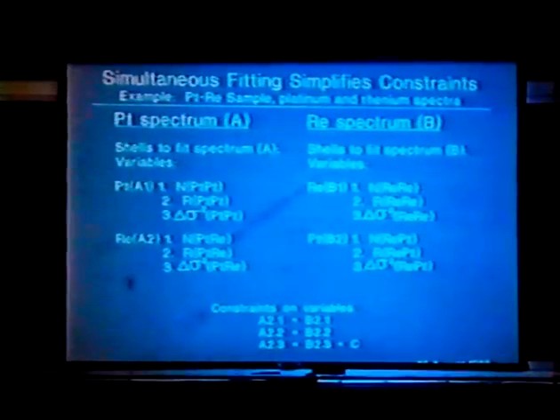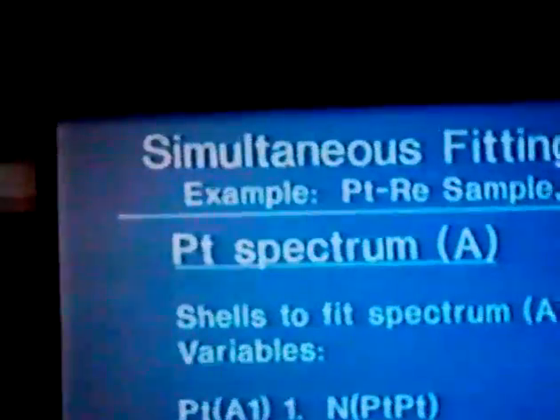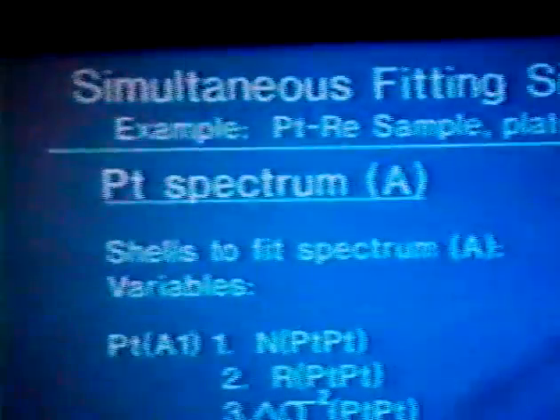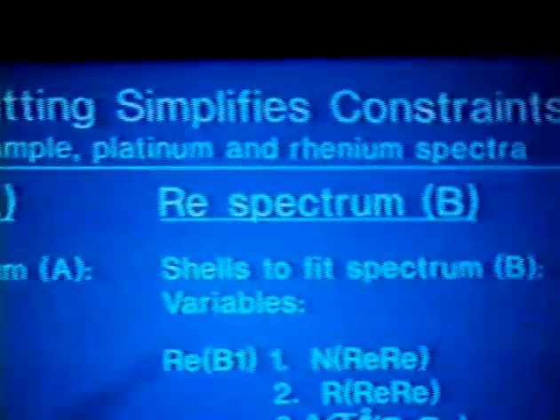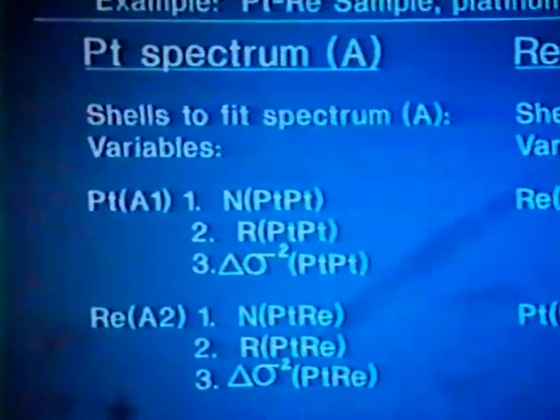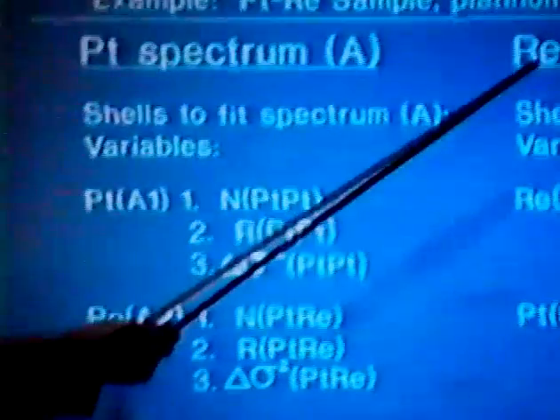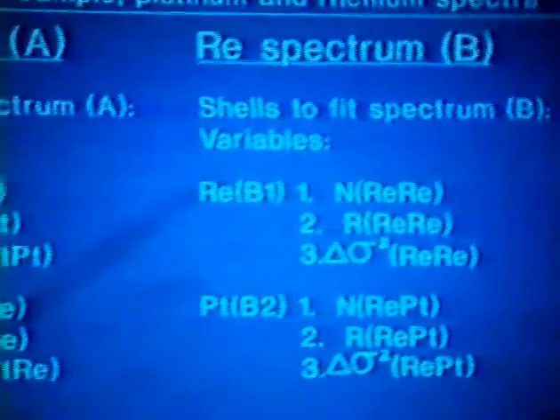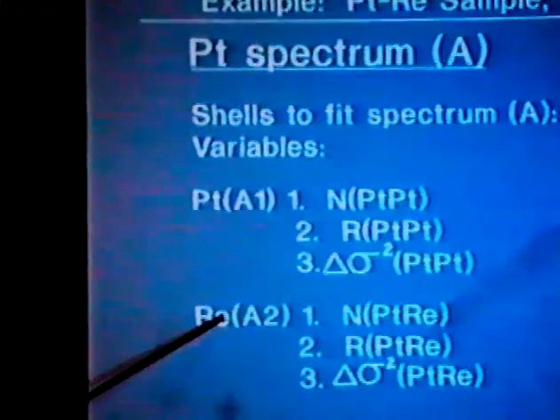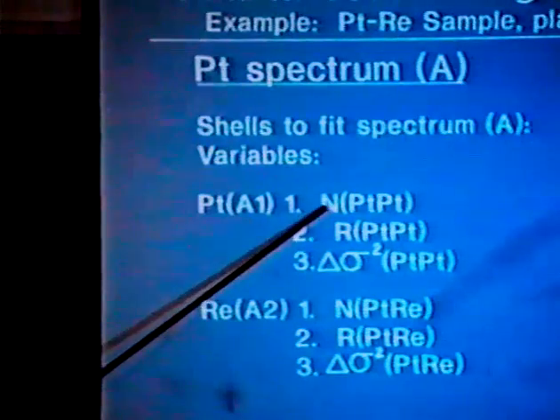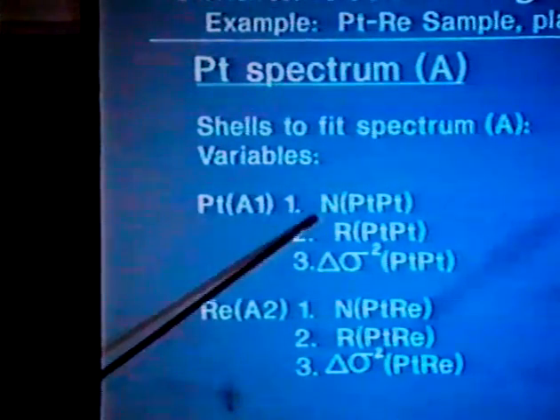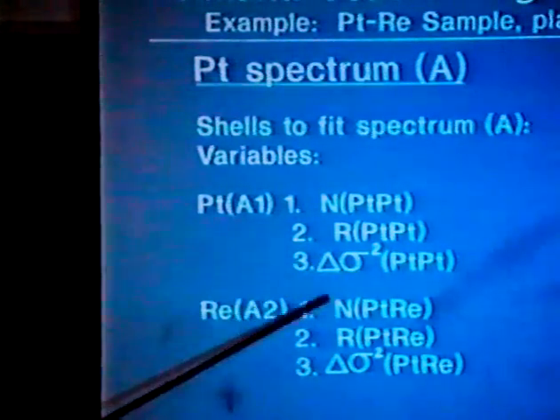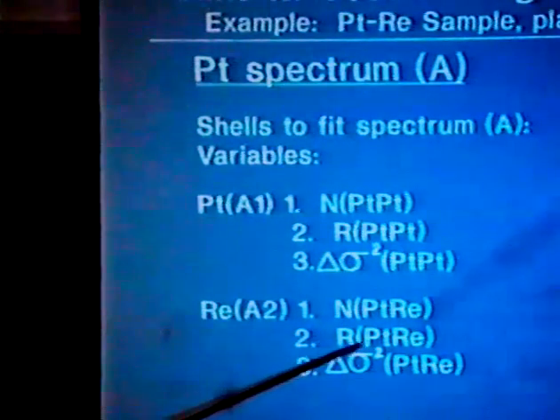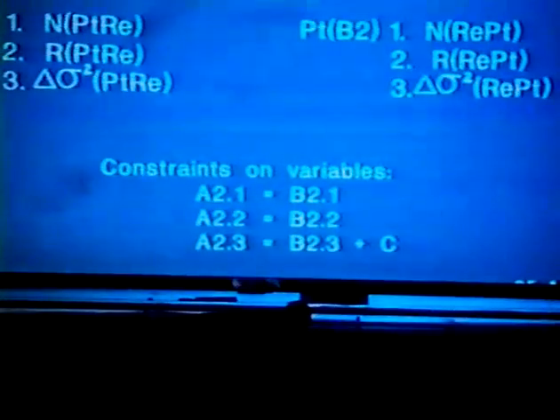This is a slide that describes the algorithm, really. And I like this slide because part of the point of this presentation is that this doesn't have to be 2 EXAFS spectra. Anytime you have a model for analysis of the spectrum, 2 different kinds of spectrum, if they contain the same parameter, then this kind of thing can be done with a computer. I'm talking now about a platinum spectrum and a rhenium spectrum. And I'm saying the platinum spectrum should be described with platinum scattering type atoms and rhenium scattering type atoms. And there's a number of platinum scattering type atoms, the platinum coordination number. There's a distance to platinum neighbors, and there's a dispersion about the distance. And then there's a number of rhenium neighbors, a distance to the rhenium neighbors, and a dispersion about the platinum-rhenium distance. The same things are true of the rhenium spectrum, all this information.